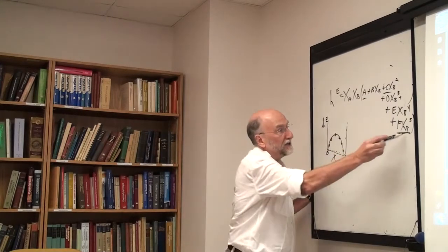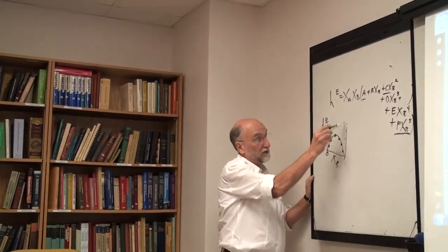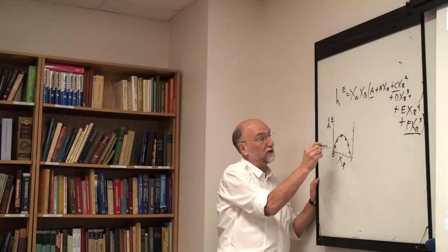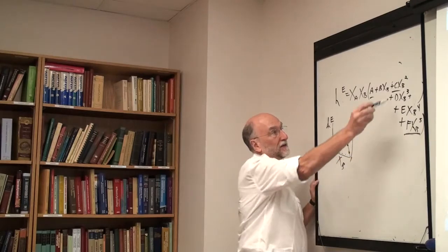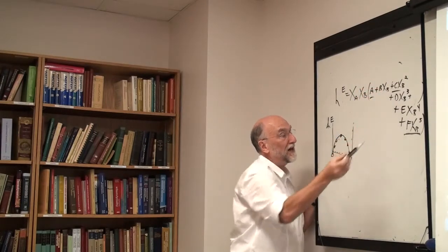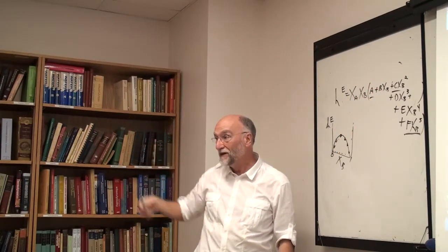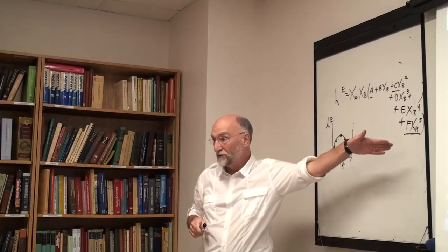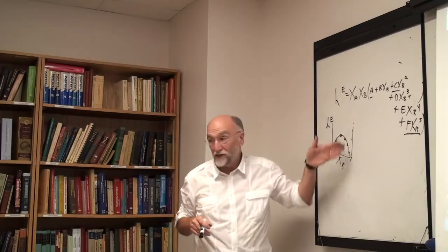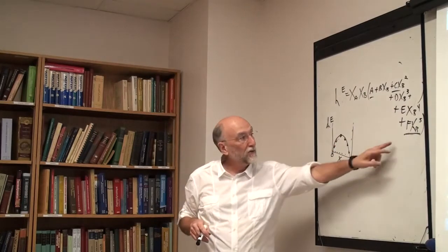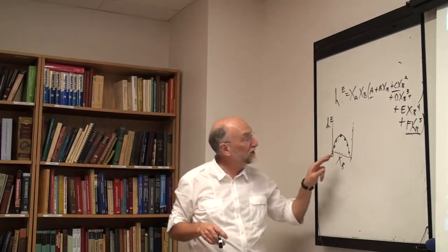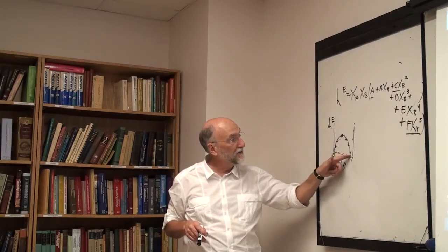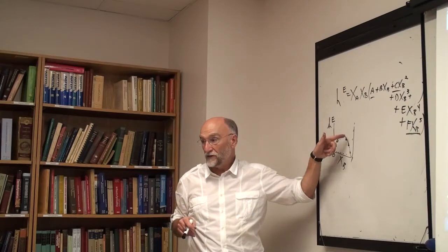So adding this term can have an effect over here, but if I want it to have any effect over here, to try to fit the curve better on this left-hand side, these coefficients, A, B, C, D, E, and F, are going to have to get bigger and bigger and bigger numerically. Orders of magnitude bigger as I add more and more terms. Otherwise, all I'm doing is fitting this end over here. So this F coefficient has to be very large if it's going to have any effect over here. However, then it has a much too big an effect on this side.